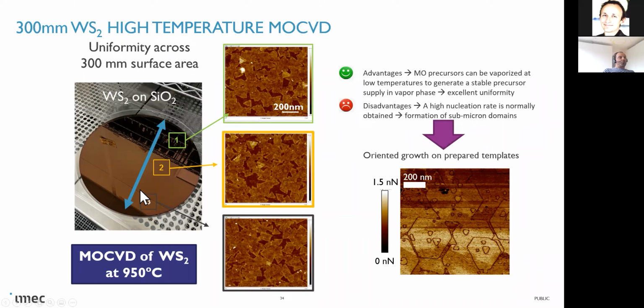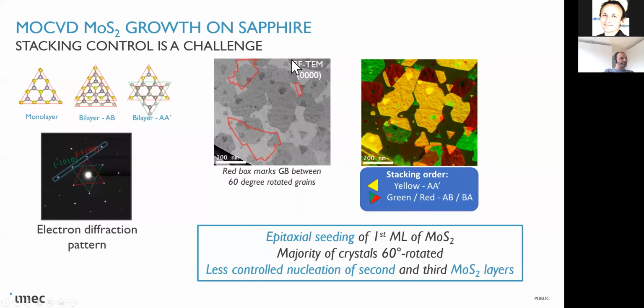The drawback that we have is that if we are working on silicon oxide, we cannot orient the grains. This is something that you can see here. But if you start to work on templates, we can see that we can improve the orientation of the grains. And this is when we are working on sapphire. This is a transferred TEM image of 1 micron. And basically what you see is that for the bottom layer, okay, we are suffering from second layer growth and third layer growth, but the bottom layer is fully organized except for 60 degree twist angles. So basically, this is suggesting that indeed the whole layer is organized and has a certain direction. And this opens, of course, the door towards growing a full single crystalline layer on top of such templates.